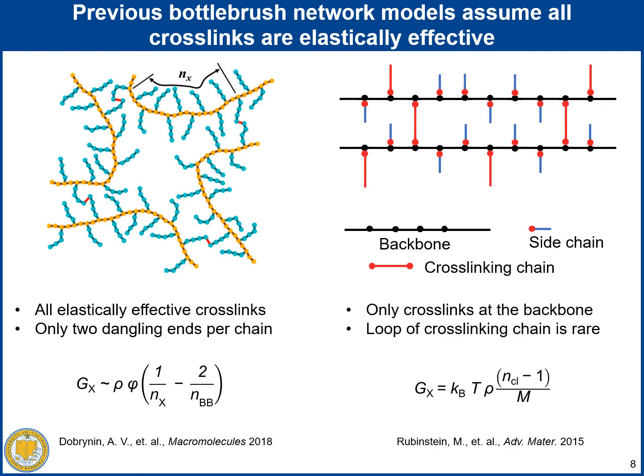In the other case, the crosslink chemistry is designed in a way such that the crosslinks are only allowed on the backbone of a Bottlebrush polymer. And because the chance of looping for both crosslinker and Bottlebrush polymer is really rare, this scenario essentially also assumes all crosslinks are elastically effective.